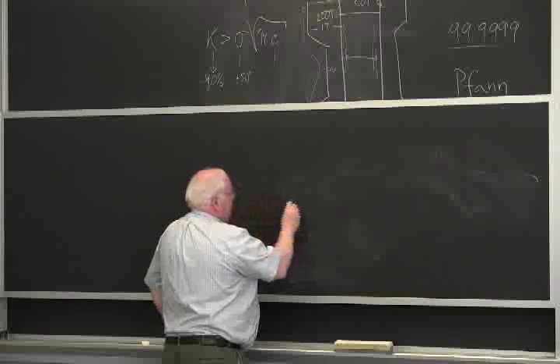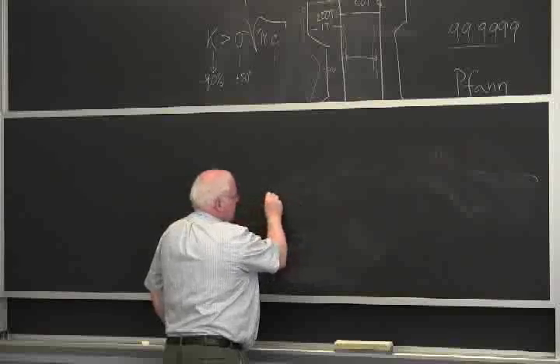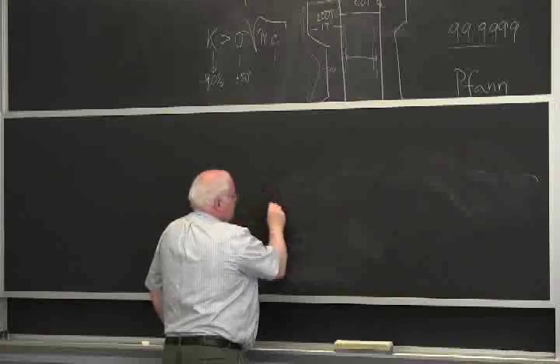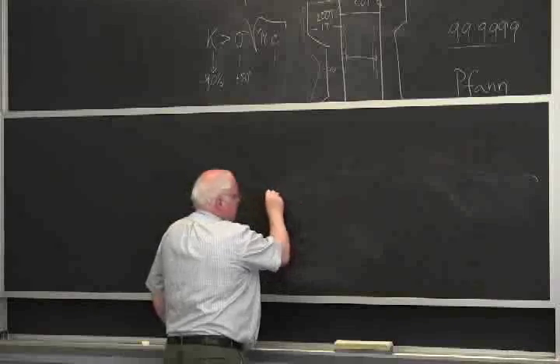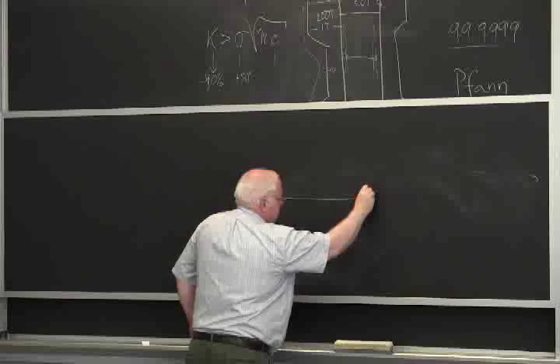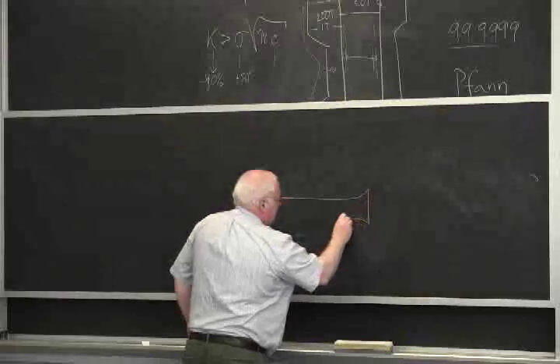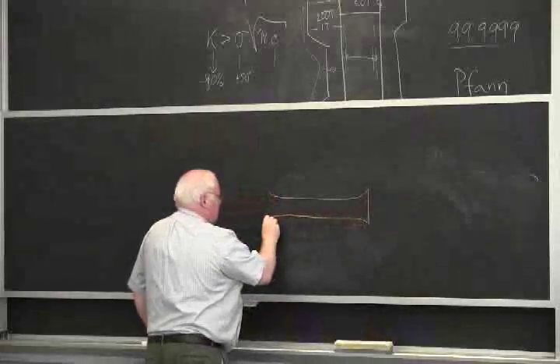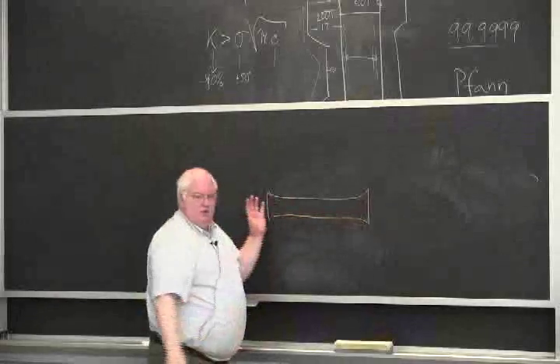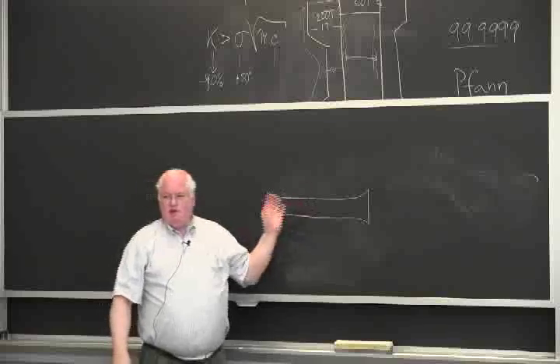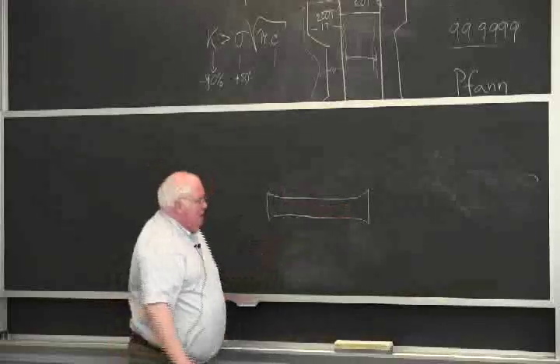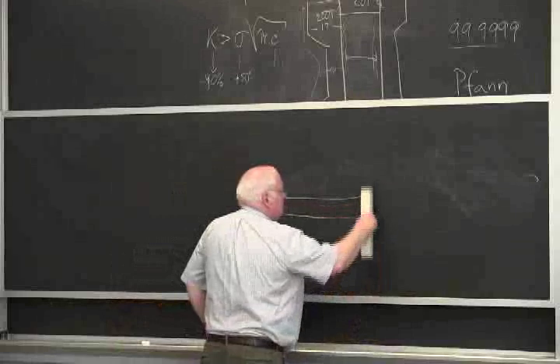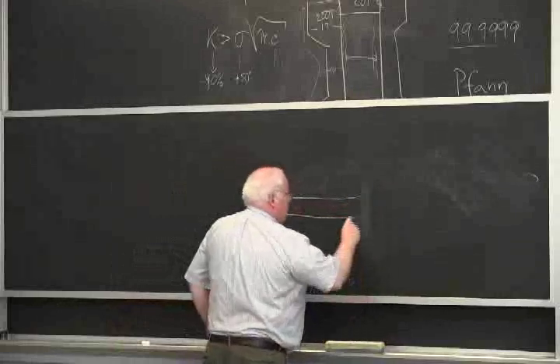And thick plate's a little bit harder to do that anyway. With the radiation, you have to clear everybody out of the mill. So they only measured at one location, but if you looked along the length of one of these plates, they were getting things that looked like this. So that's what the student did. She went out and she had a thickness gauge after they finished rolling. She actually mapped them. Some of them had it on both ends. Some of them only had it on one end.